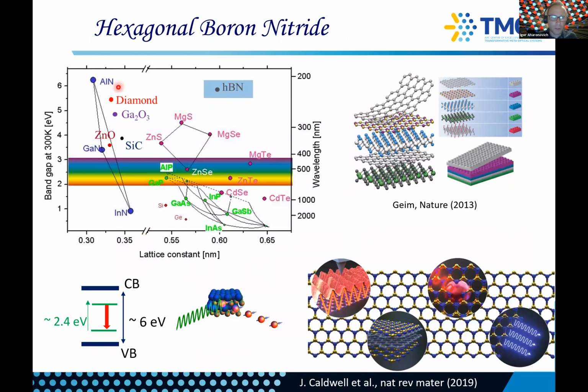And if you look at this diagram of wide bandgap materials that can host these atomic defects, hBN is the only system that can really be exfoliated into a 2D type. And so that is why we chose hBN. It has a very high bandgap, about 6 eV, and you can excite it with a green laser like you would do with your defects in diamond or silicon carbide. And of course, you can then assemble it into devices. And I will show you a few examples.